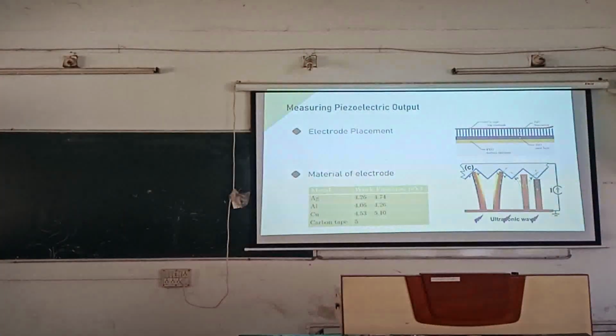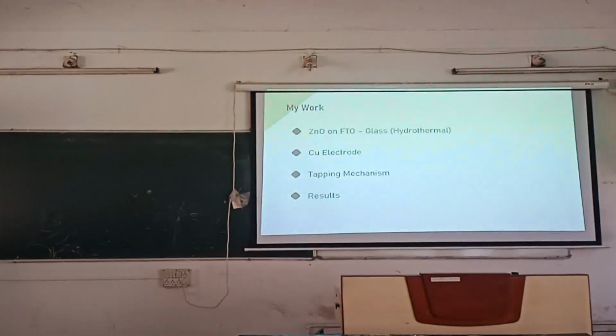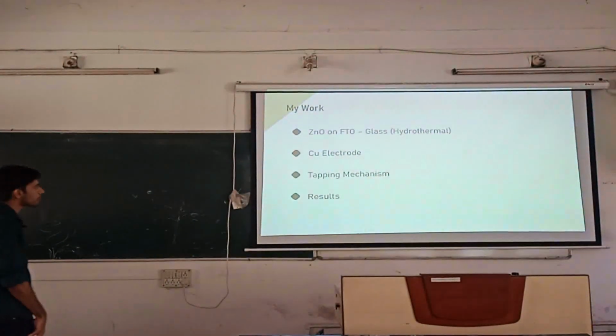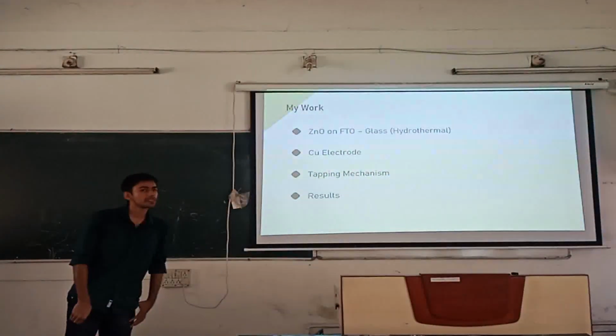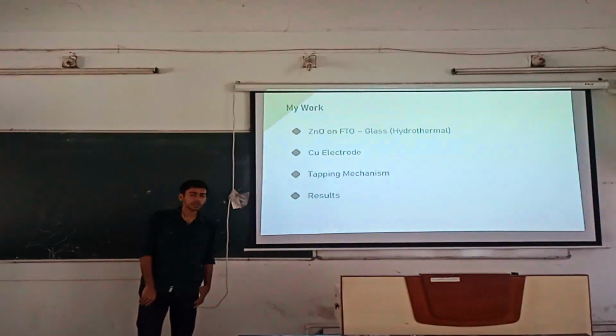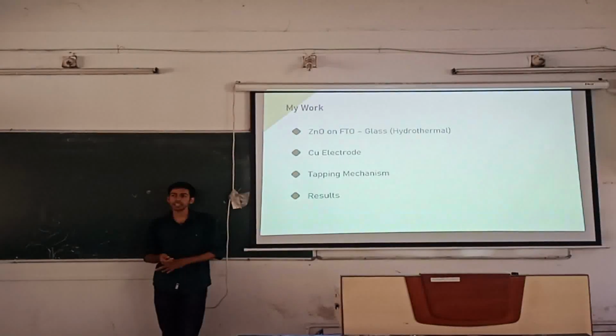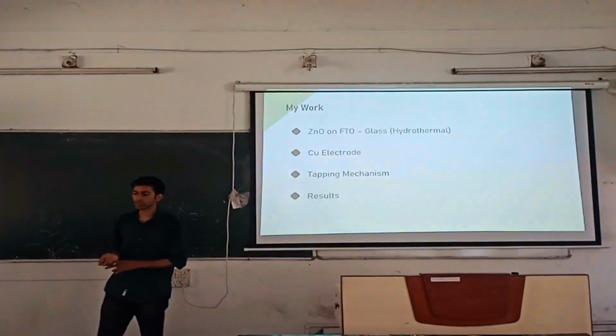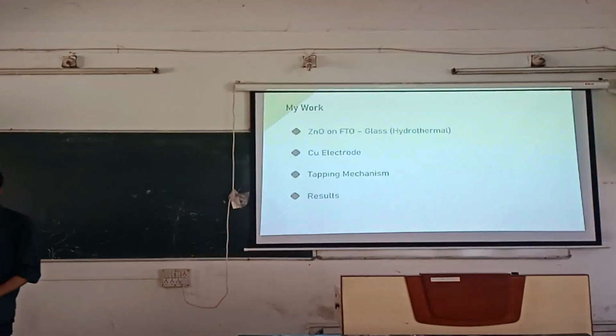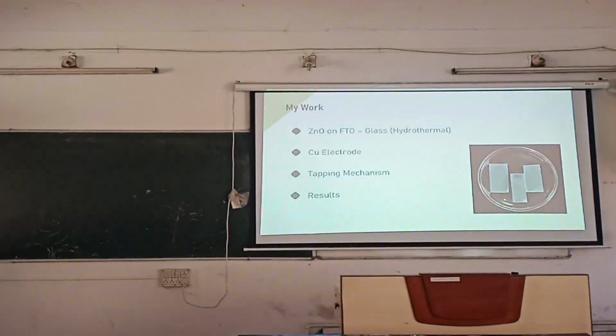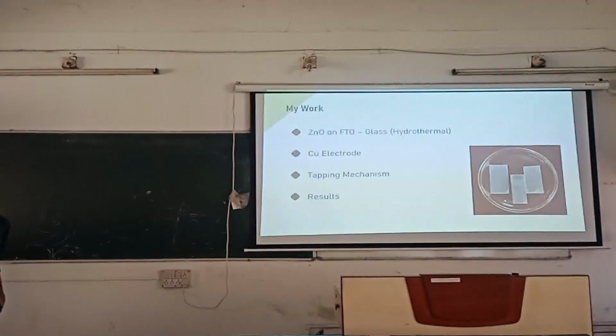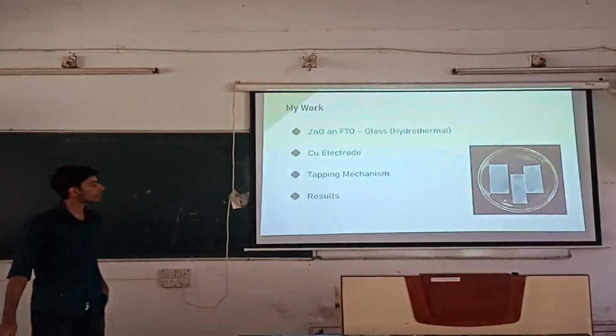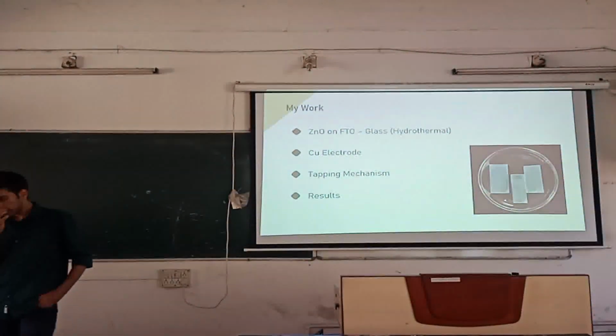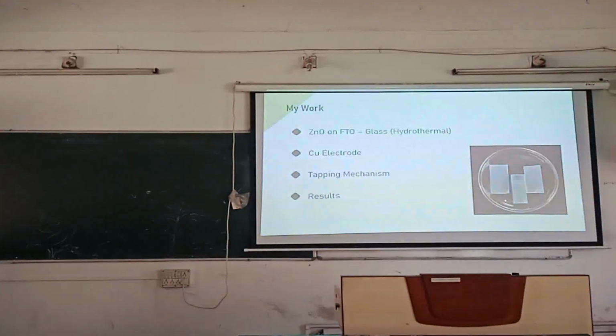In my work, I first grew zinc oxide nanowires on glass. It was not a normal glass, it was a conducting glass, called FTO coated glass. After growing, it looks like this. This glass is actually transparent, but after depositing zinc oxide, it becomes like this. Growing the zinc oxide nanowires is a 1-day process.